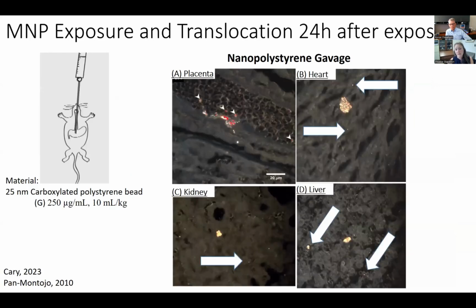We repeated these studies using a gavage technique instead. So instead of putting them into the maternal lung, we put them in the maternal GI system, directly into the stomach, and did the same thing. We waited for 24 hours after exposure, then sacrificed our animals. We were able to identify these particles, again using hyperspectral microscopy, in the rodent placenta, in the heart, in the kidney, and in the liver of the fetal pups after gavage. And that's not to say that we didn't find them in the other tissues. That's to say that we didn't assess them in the other tissues. So that's a point to keep in mind as well.